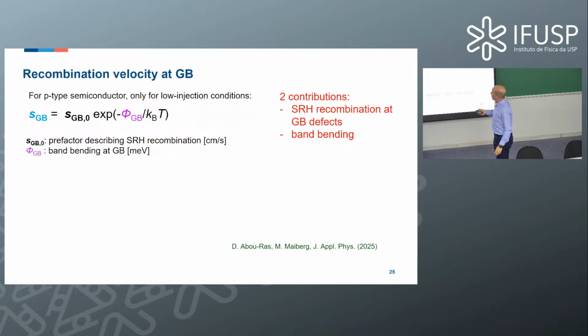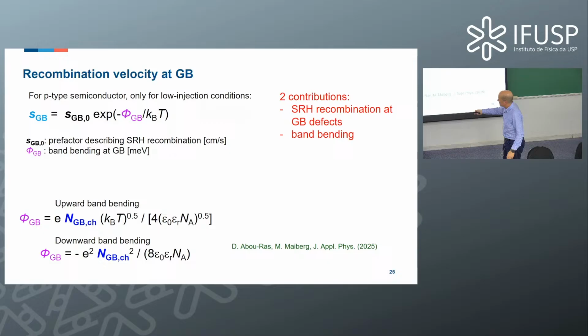Instead, what we can come up with, and this is detailed in this publication, is that the recombination velocity can be described by two parameters. One is a prefactor that contains the Shockley-Read recombination. It's a recombination velocity only taking care of how far the defects at the grain boundary contribute to enhance Shockley-Read recombination. Okay? This parameter here in the exponential function is the barrier height, yes, the barrier height that we calculate from the redistribution of free charge carriers. So there are two parameters, and in the publication we derive these equations here for upward and downward band bending. I mean, this one here is already known in the literature, but I was quite astonished that there's absolutely no publication about the upward band bending, so the barrier for the minority charge carriers.